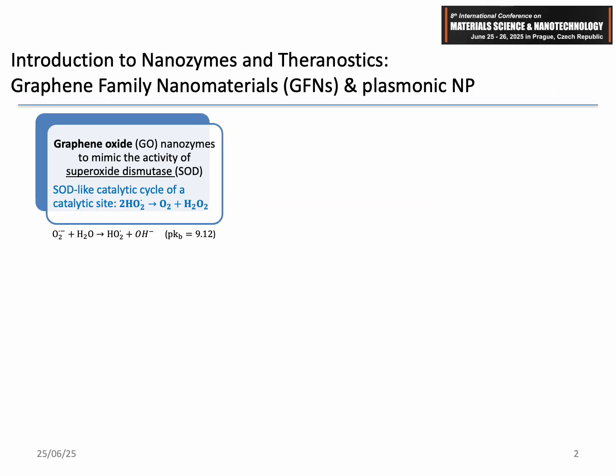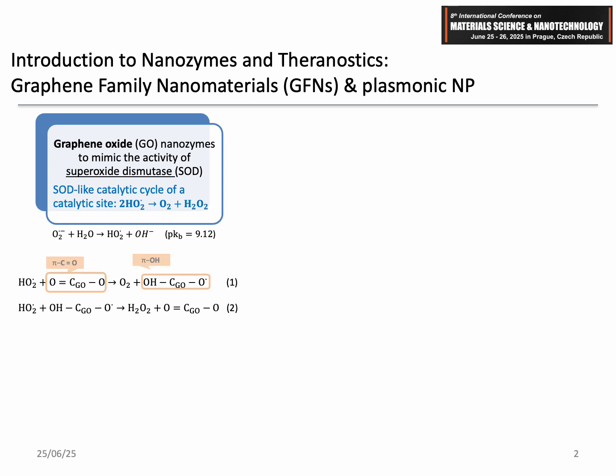So the graphene-based nanozymes emulate the catalytic function of superoxide dismutase, which is a class of metalloenzymes that convert two superoxide anions into triplet oxygen and hydrogen peroxide. And the SOD-like activity of graphene oxide proceeds through a two-step redox mechanism.